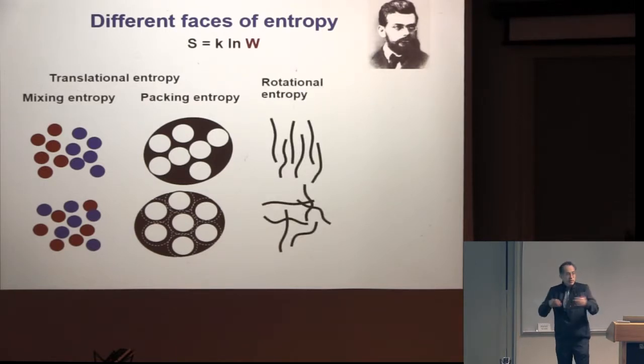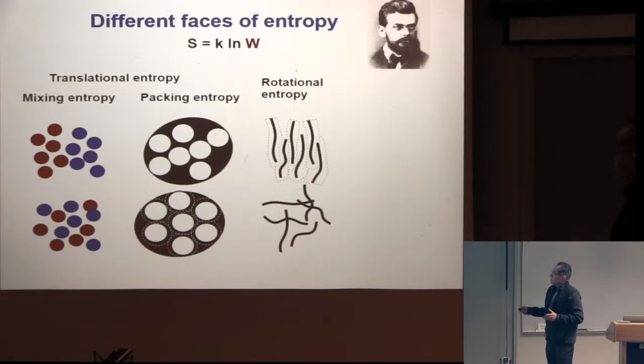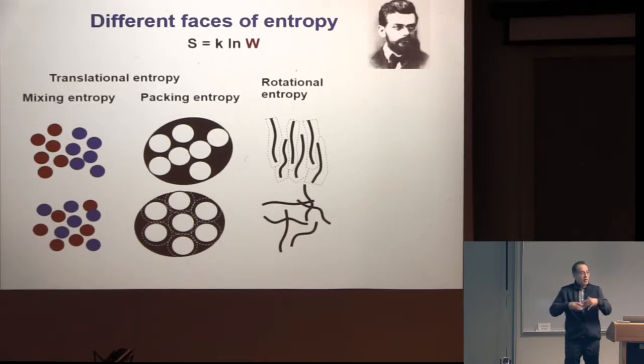In the case of these rigid rods, you may also recognize that this system will have more rotational entropy compared, say, to this. But then again, if you increase the concentration high enough, it could be that under these conditions, the packing entropy can increase by alignment, and this increase in packing entropy can compensate for the loss of rotational entropy that you have in this system. And in fact, that's how entropic liquid crystals come about, like, say, nematic phases.